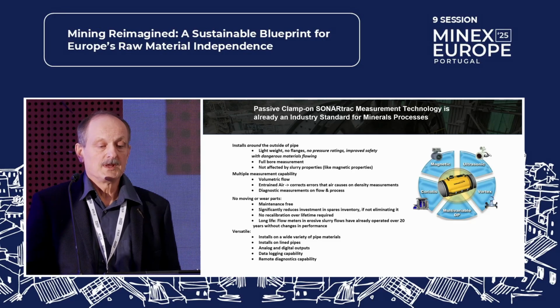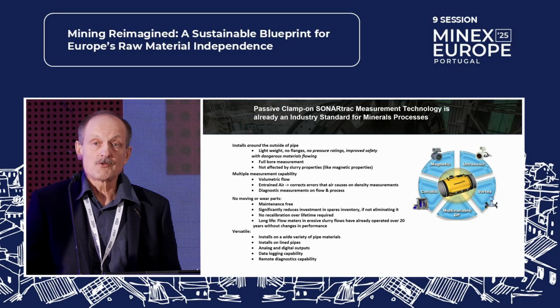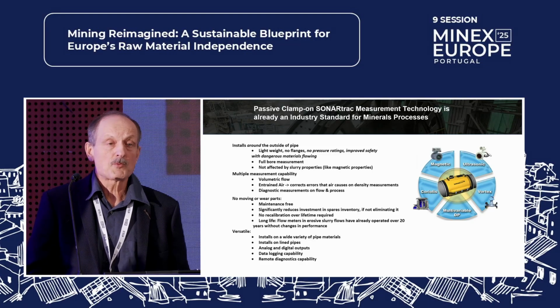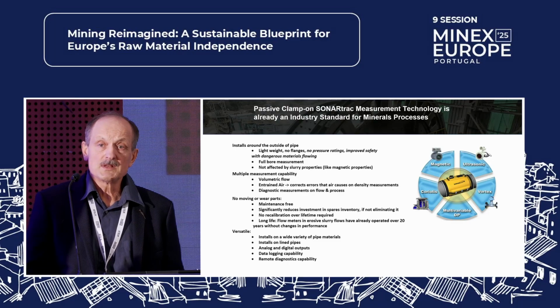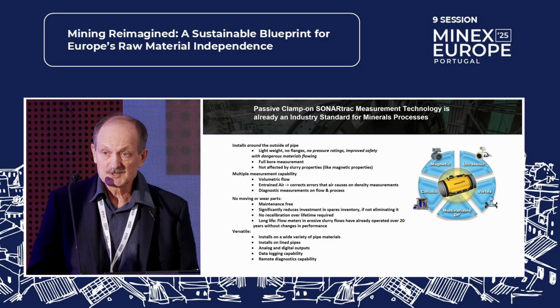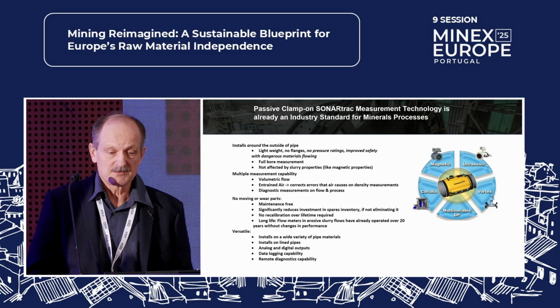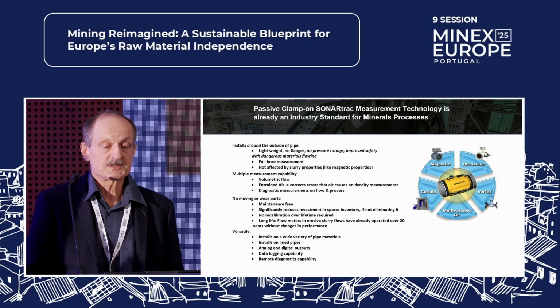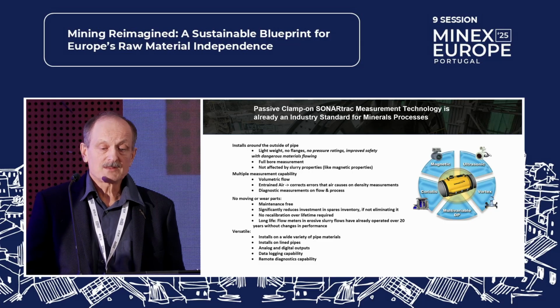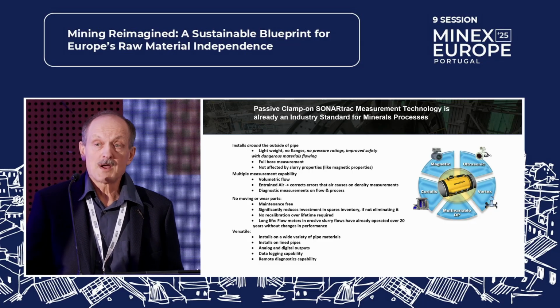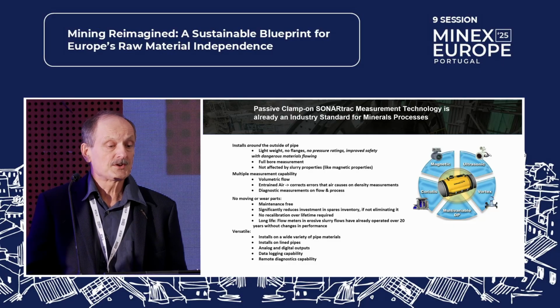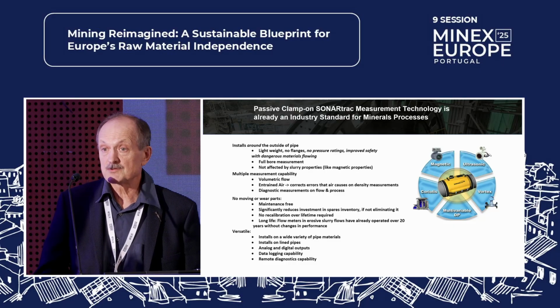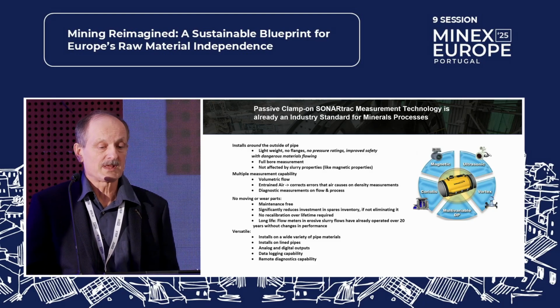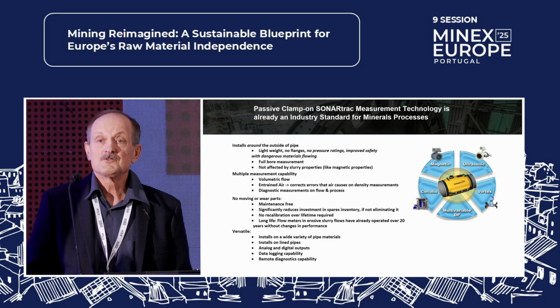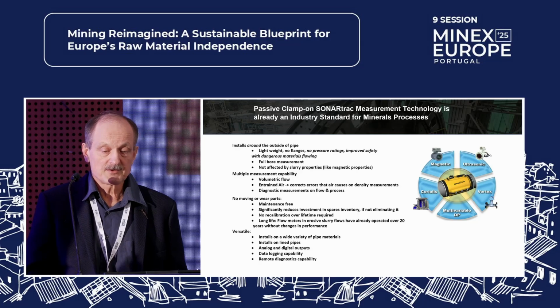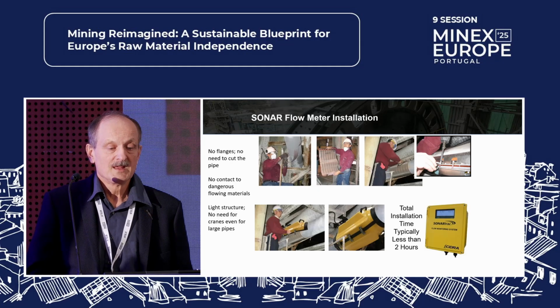We have developed a passive clamp-on sonar technology that measures the propagation velocity of turbulences that carry the solids forward. So it's solids flow measurement there in question. In addition to that, we can measure the volume occupied by bubbles at that measurement position, and we can correct the errors bubbles are causing for density measurements. And you will get, of course, warnings when there is too much air in the slurry, so you can prevent the blockings.